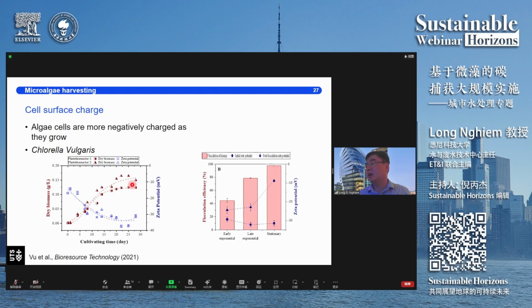And obviously, if you look at the biomass content, you can see that the biomass content of the solution increased until it's basically stationary phase. So clearly, there is some impact from the surface charge of the membrane of the microalgae cell. However, if we look at the microalgae cell after flocculation, you see that it doesn't need to go back to zero in order to have complete charge neutralization, and we can still get very, very high efficiency. So yeah, charge is an impact, but probably not a very significant factor.